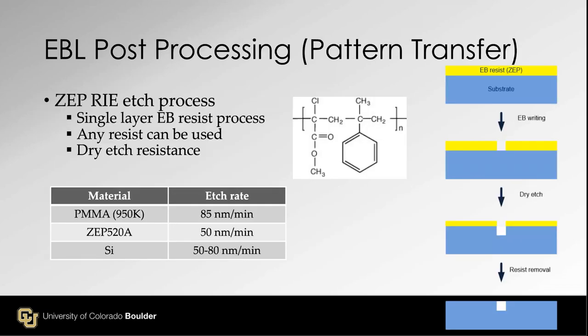This is the second example for pattern transfer. Instead of the lift-off process, you can use etching. In this case, the e-beam resist, a different resist I used here, acts as an etch mask. You start the same way, with the substrate, put on the e-beam resist, write, and develop, removing the exposed area, so it is still a positive resist. Then, instead of depositing a thin film layer, you do a dry etch. Then you remove the resist, and now you have a hole in the substrate. That's a different way of doing the pattern transfer.